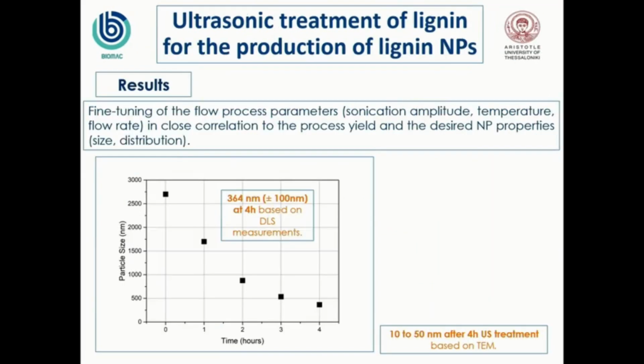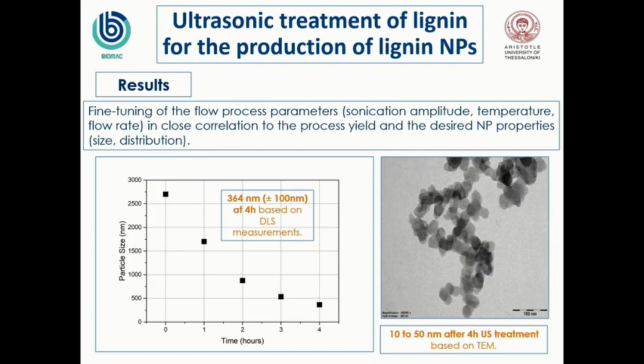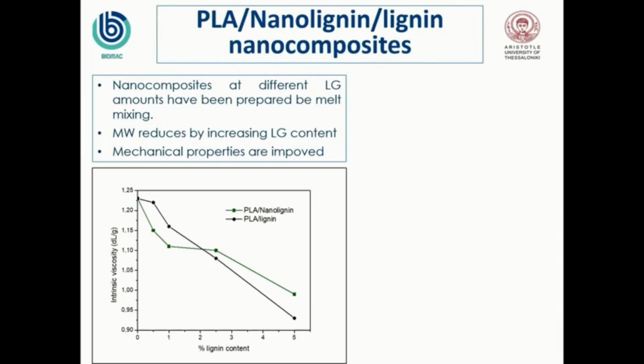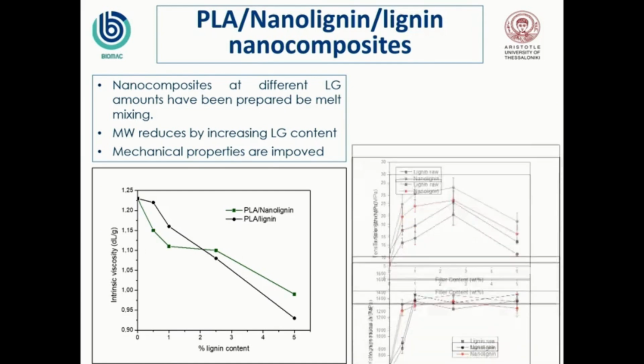As you can see here, starting from sulfa-lignin, we start with a particle size of about 2,500 nanometers, and after some treatment, we can see that it was reduced to less than 500. These are DLS measurements, and with transmission electron microscopy, we can see that we reduce the size to the nanometer level. And this was used in comparison with lignin to produce some reinforced PLA nanocomposites.